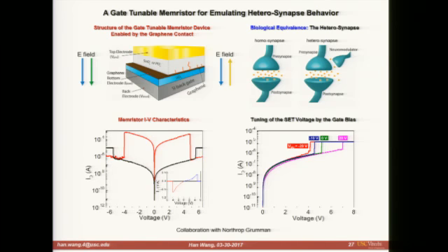When the gate bias becomes less negative, to 0 or even positive, the gate starts to oppose this filament formation, and the filament is more difficult to form, so the set voltage has to be higher than previously. This already gives you an indication about how the gate field can influence the filament formation process.